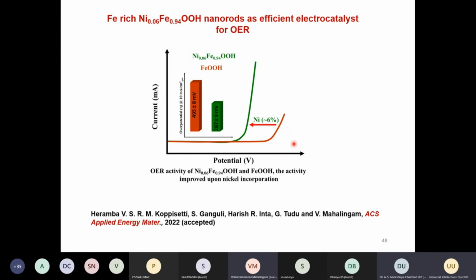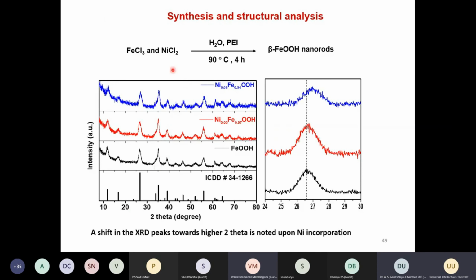What we found is the 6% shows a much better activity compared to the only iron oxyhydroxide sample. So nickel is very much needed for them, but in this case, nickel is only a very small percentage. It's mostly an iron-rich material. The synthesis is quite simple, but it's a little tricky. The conditions have to be very precise.